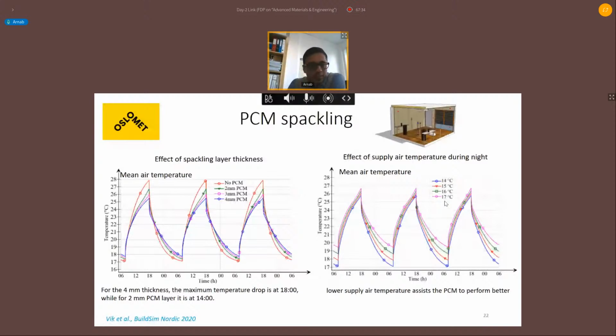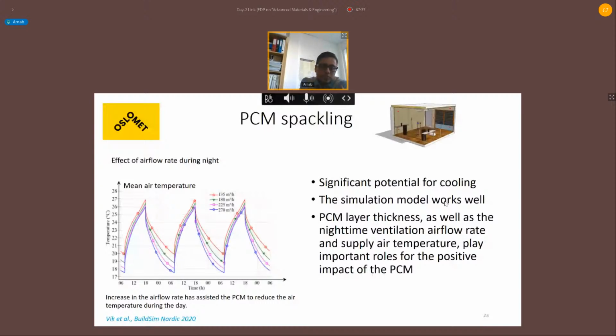And we also looked into the air flow rate, which in our base case is around 230 meter cube per hour. It means sufficient cooling is done, which is this near the magenta line. If you increase it, naturally it will lower the temperature, and if you decrease the air flow rate, then naturally the cooling is not sufficient to recharge. So we get more effect in the morning time, where we need to actually recharge.